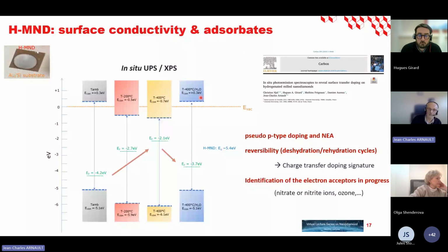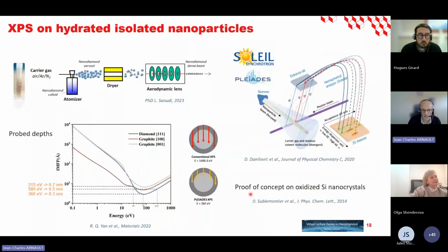There is some difference in the position of the Fermi level, but this suggests that it's a reversible phenomenon, probably due to adsorbates. Of course, we cannot say for the moment what the adsorbates are. We have different candidates, but to be honest, we are also thinking about some specific interaction with water molecules. So to see that, we would really like to probe the shallow surface of these particles.